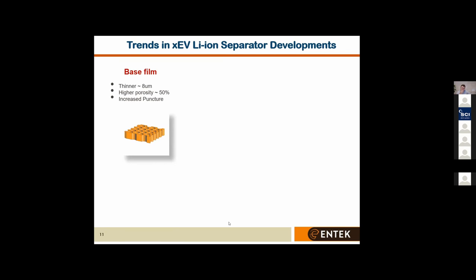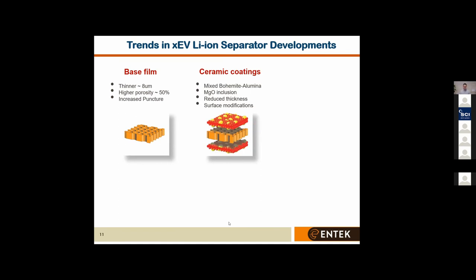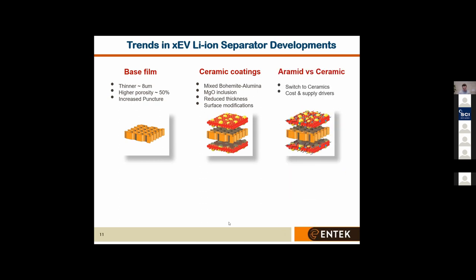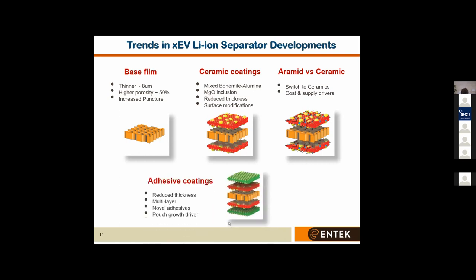So let's have a quick look at the roadmap or the trends that we see for development. Base film, we see that going thinner, around about 8 microns, a higher porosity, approximately 50%, and of course, an ever-increasing demand for increased puncture. For the ceramic coatings, we're seeing increased percentage composition of boehmite in that mixed ceramic coating, potential magnesium oxide inclusions, reduced thickness and surface modifications as well. We look at a lot of the Tesla cells in operation at the moment, quite a few of those have actually aramid coating, not so much ceramics. And we see that shifting, both in terms of cost and supply drivers, towards ceramic. And then adhesive coatings, reduced thickness, multi-layer, as with our cells, so 5-layer, looking at novel adhesives, and it's really the growth or the conversion to pouch form factor that's driving that growth.